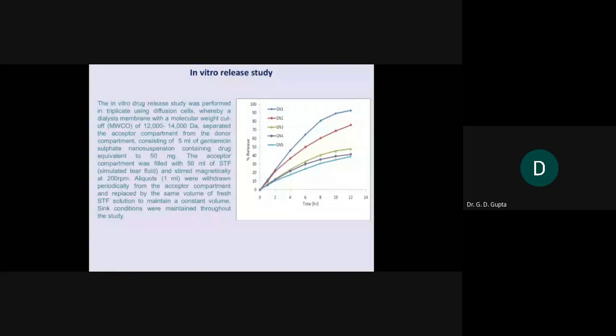Next, the in vitro release study. Similarly, we performed the in vitro release study using a dialysis membrane with a molecular weight cutoff of about 12,000 to 14,000 Dalton. We took 5 ml of gentamicin sulphate nanosuspension, and for the dissolution media we used simulated tear fluid. You can see in the graph of formulation GN1 that about 90-93% of the drug is released